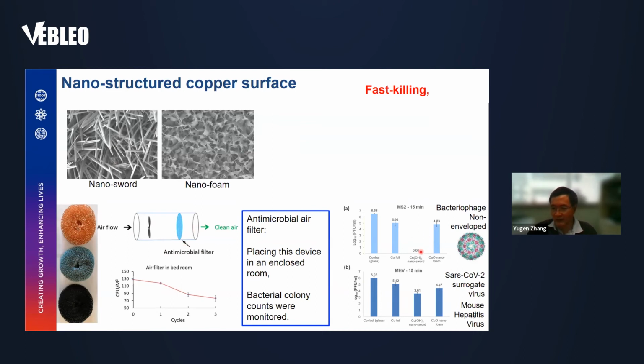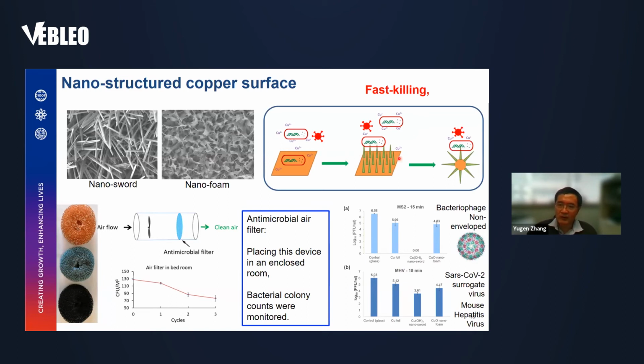And showing here is the antivirus test. We take this MS2, the bacteriophage, and also we take this MHV as a surrogate for the SARS-CoV-2 virus. And these materials demonstrate very good fast killing properties against these two viruses. So for the killing mechanism as shown here, with these nanostructures, on one side, it can kill the bacteria using this nanostructure. On another side, with a much, much higher surface area, they can have a fast release of copper cations into the surroundings. And these copper cations can kill the bacteria and also the virus. So that's why these materials have fast killing and antibacterial and also antivirus properties.